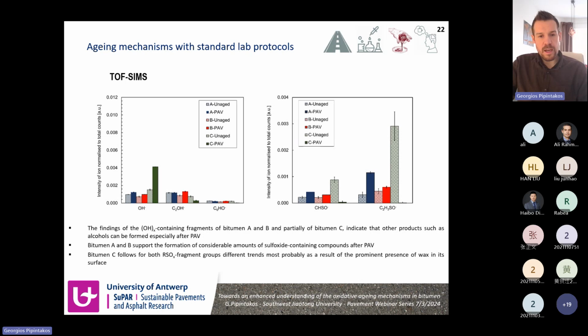Finally, TOF-SIMS was used before and after long-term aging with PAV. The findings showed that the hydroxide-containing fragments were increasing for bitumen A and B, which indicates that products like alcohols can be formed after PAV. Also, for bitumen A and B, we have formation of sulfoxide-containing compounds, as you can see on the right graph, whereas bitumen C probably didn't show the same trend because of the aliphatics that covered most of the bitumen surface, as was shown previously in high-resolution images.